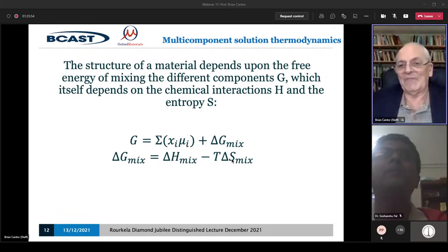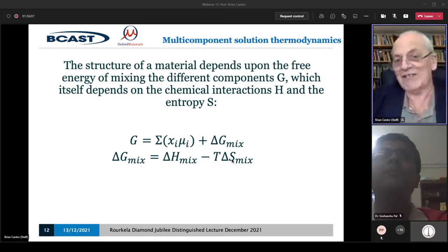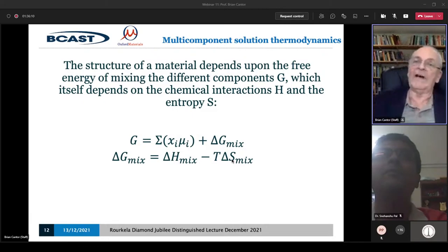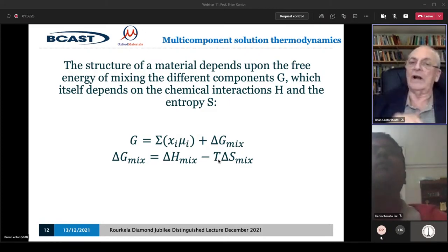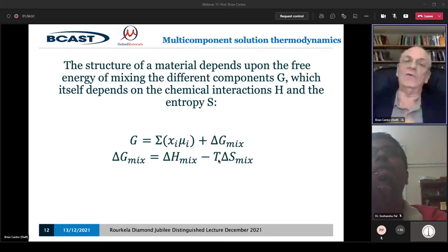We've now had enough time. It was discovered in 1980. The first paper was in 2004. It only began to be studied in detail in 2010. We've only had 11 years. So people only began to do these long-term annealing experiments a few years after that. So we've only just begun to understand. But people have done it enough now. Above 800 degrees, it seems to be completely stable. So above 800 degrees, it's thermodynamically stable. Below 800 degrees, it's thermodynamically unstable. And there's a region between about 600 and 800 degrees where if you anneal it for years and years, it will decompose. So that's the Cantor alloy.